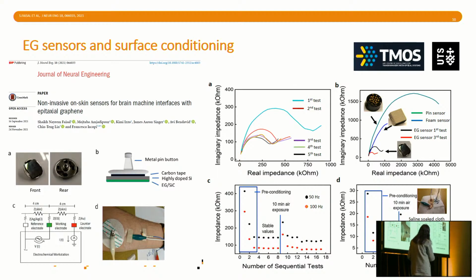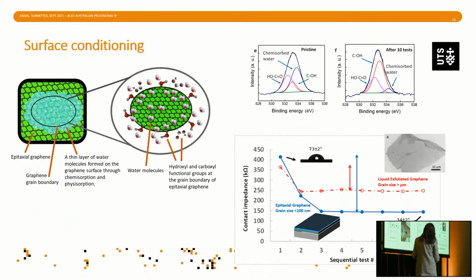And this is really great because it makes the sensor really thin compared to the bulky, dry sensor, really compact and resilient, and also with a much better impedance compared to commercial sensors. Now, what I wanted to say once again is that in this case, if you were going to use a perfect graphene with large grain sizes, it wouldn't be a good choice because that type of graphene is going to be quite hydrophobic.